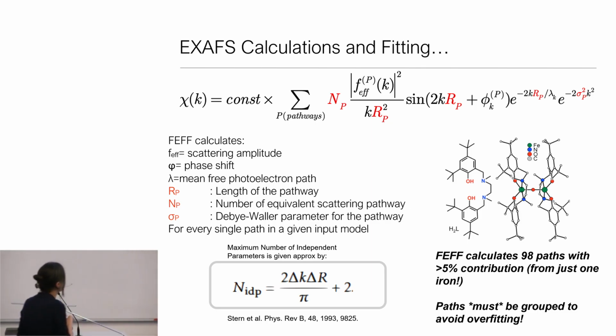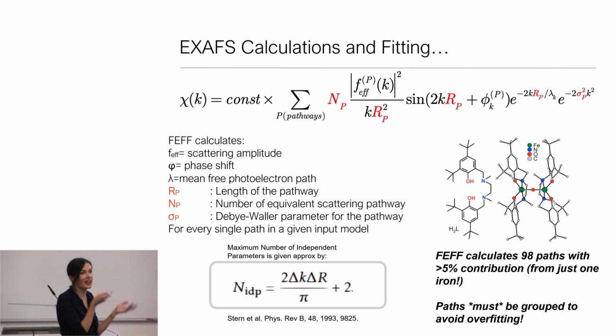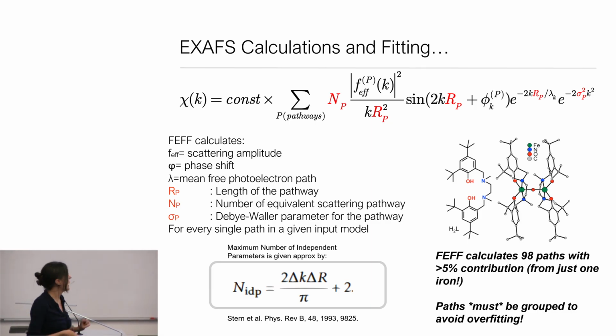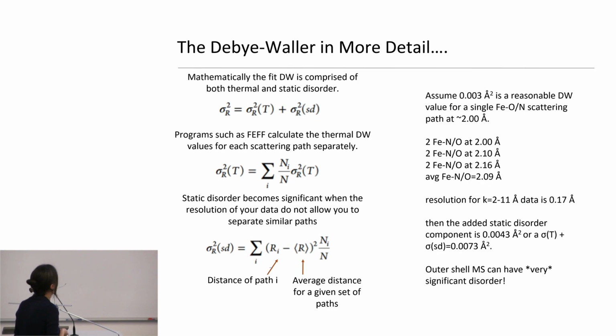So normally this is our expression for the number of independent parameters. It goes as 2 delta k delta R over pi. So most of the time we're dealing with a number of free parameters that's closer to maybe 10 to 15, but certainly not hundreds, which is what I would need for these 98 paths. And so what we intrinsically do when we calculate EXAFS is to start grouping paths that are related to each other.